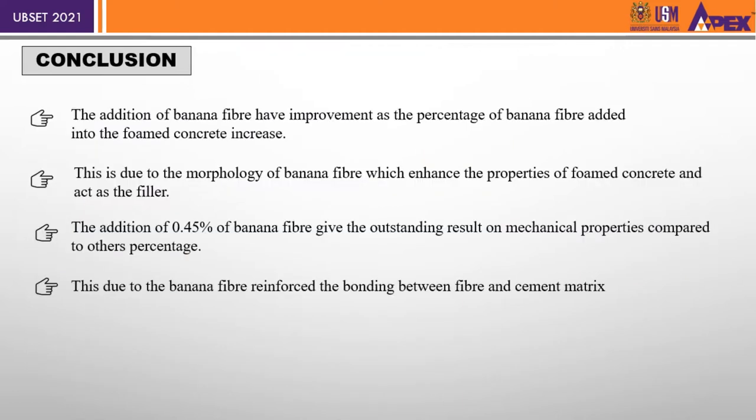For the conclusion from my research, the tests conducted on the durability properties show that the foam concrete with the addition of banana fiber improves as the percentage of banana fiber added into the foam concrete increases. This is due to the morphology of banana fiber, which enhances the properties of foam concrete and acts as a filler that gives a compact composition of the microstructure, in this way lessening the size and